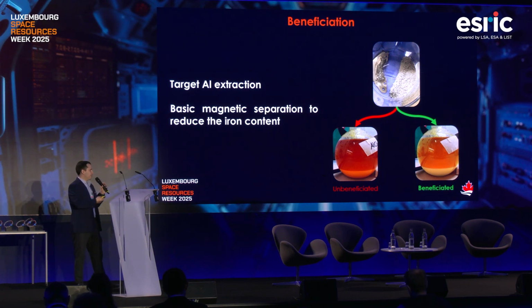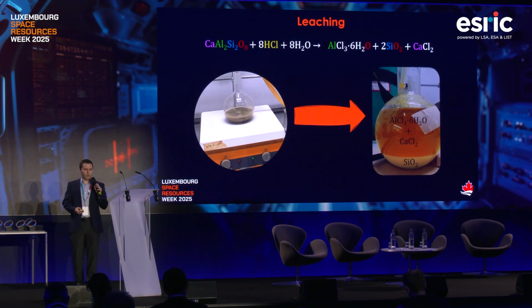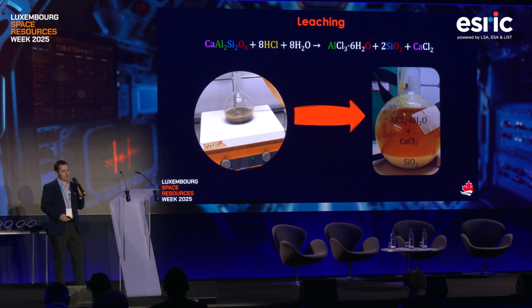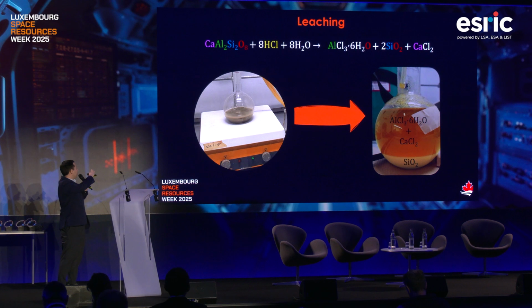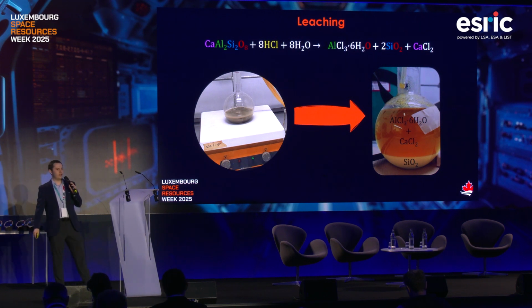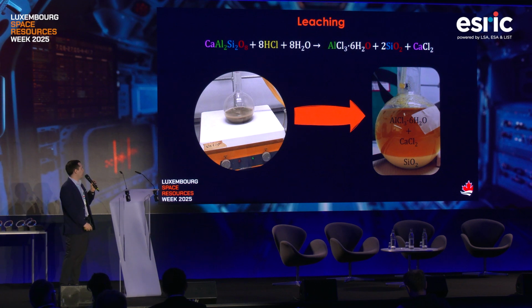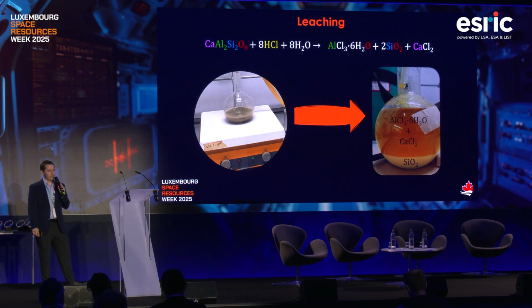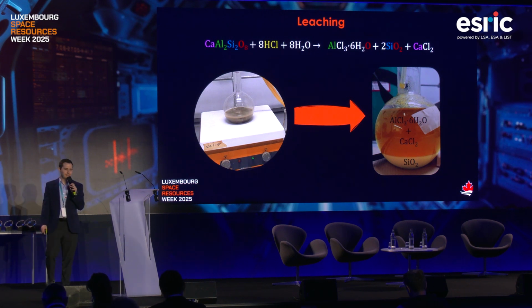So after beneficiating the regolith, what we did was the leaching step. So that's the chemical reaction. Mostly we have our anorthite. We're using hydrochloric acid, and then we produce aluminum chloride hexahydrate, silica, and calcium chloride. So all of those elements could be useful.